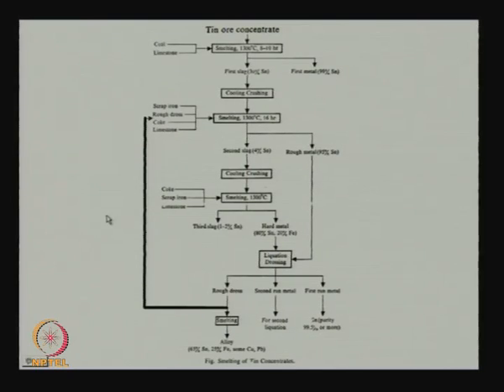So, in the next process we are producing a second slag which would have only 4% tin as against 30% tin here, and we produce a rough metal which will have 95% tin as against initially 99% tin. The second slag would again be cooled, crushed, and go through a third smelting operation. All these smelting operations will be in the reverberatory furnace. I have shown pictures of the reverberatory furnace earlier. I will show it again when I start discussing copper metallurgy.